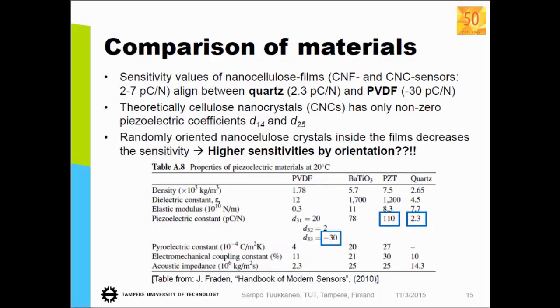So okay, here is still a comparison. There's a table with conventionally used piezoelectric materials, like quartz and this PVDF, which is normally used in acoustic piezo elements. So nanocellulose aligns somewhere between the quartz and PVDF in these values. Theoretically, nanocellulose has only the piezoelectric coefficients D14 and D25, but when you have randomly oriented crystals in the film, you can detect whatever piezoelectricity. So we are actually not measuring these values, but something coming from randomly oriented crystals. So this is something we are going to work on in the future.